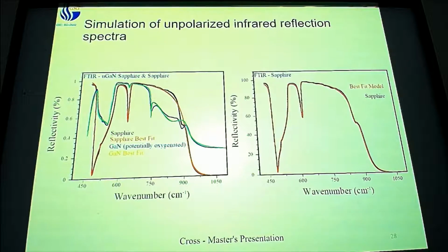The model that we're defining is based on the understood structure of the material. So from here to here, I believe we're adding effectively 4 terms, if I remember correctly. But each of those terms is based on the actual physical structure of the material. Okay. So for each of these curves here, that curve there and this curve here in the black, right here and right here, there is a phonon, which is not expressed in this model. So by expressing that phonon, because we're dealing with both polarizations and not just a single polarization of light, I can actually fit those 2 terms.